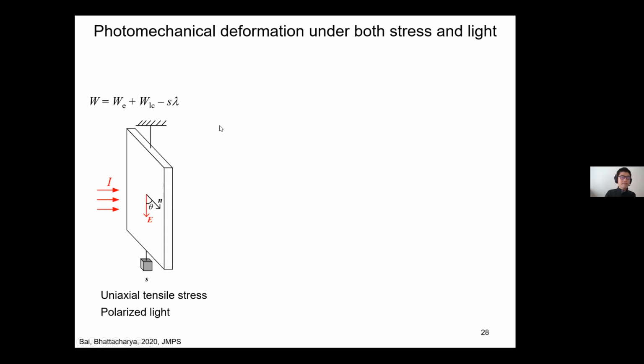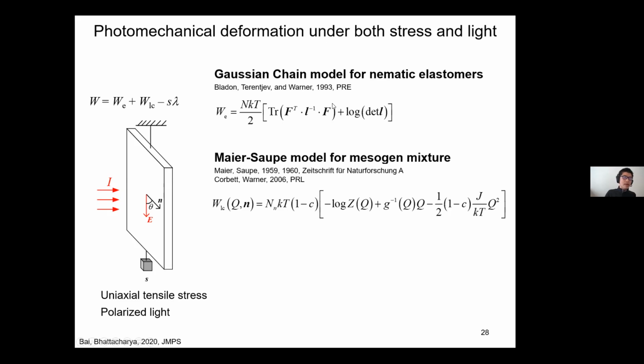solved. Okay, so I can write my free energy. I can use a Gaussian chain model by Bladon, Terentjev, and Warner. This is the classical liquid crystal elastomer model. If you drop this L term, you can see this is nothing but a neo-Hookean model. Okay, so this takes care of the anisotropy in the material.